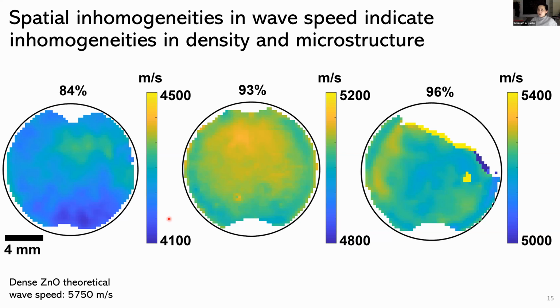The first one was that you see that there are spatial inhomogeneities in the wave speed, even within a single sample. So when we look at the 84%, there is a lack of total uniformity in the wave speed for the whole sample. This reflects the fact that ultrasound allows us to now spatially map how the sample is actually densifying through the sintering process, rather than just getting a bulk value that represents the whole piece. So in doing this, we were also able to identify some of the things that were happening in terms of the evenness of the pressure applied on the parts, the evenness of the temperature distribution of the part, as well as that liquid phase distribution.